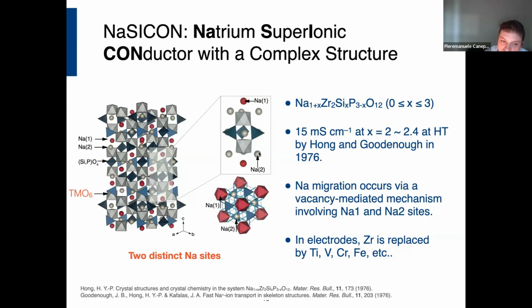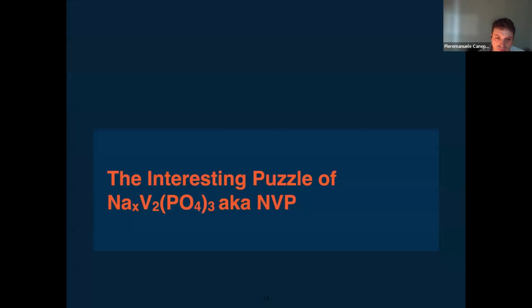Of course, you need a vacancy, so a vacancy, or a number of vacancies, is introduced. Vacancies are introduced by tuning the ratio, at least in the solid electrolyte, between silicon and phosphorus. The more silicon you introduce, the fewer vacancies you introduce, and the more phosphorus you add, the more vacancies. In this tie line that goes from x equal to 0, meaning 1 sodium per formula unit, to x equal to 3, meaning 4 sodium per formula unit, you can explore all sorts of silicon and phosphorus compositions.